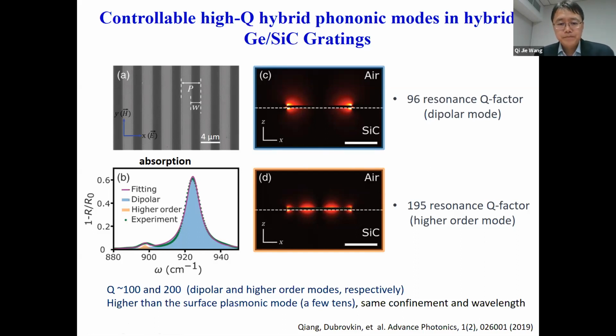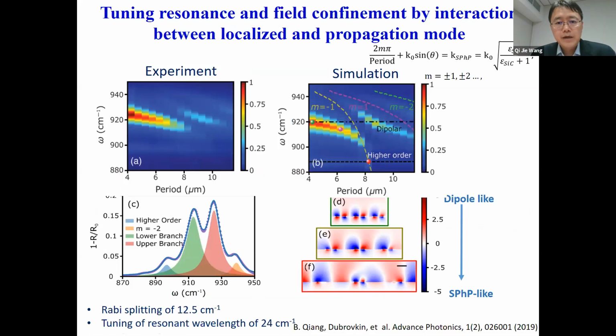And you know, this number is higher than those of a surface plasmon mode in the same wavelength region under the same confinement and the same wavelength. Okay, so that shows the advantage of Phonon-Polaritons. And then such a localized mode will be coupled with the propagation mode. So here the figure on the top right shows such coupling. So as you can see, at the frequency of 920 inverse centimeter, this corresponds to the dipolar localized mode,